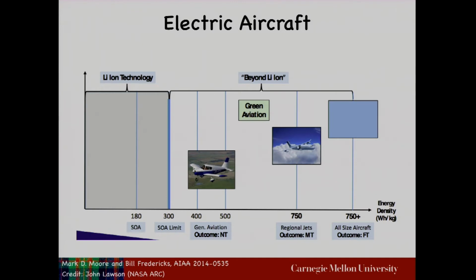Now, if you want to access general aviation, which also includes things like commercial business jets and so on, you need to access an energy density of about 400 watt-hours per kilogram. The best cells that we get from state-of-the-art, which could be the Tesla cells or things like that, are somewhere in the 180 to 200 watt-hours per kilogram at the pack level. And with lithium metal, you can get to about 300, maybe 350. But to reach the 400 to 500 range, you need a second change to the battery chemistry.